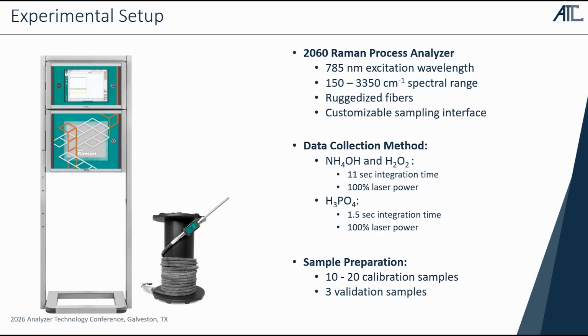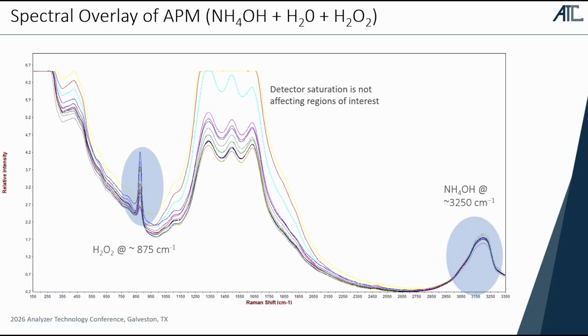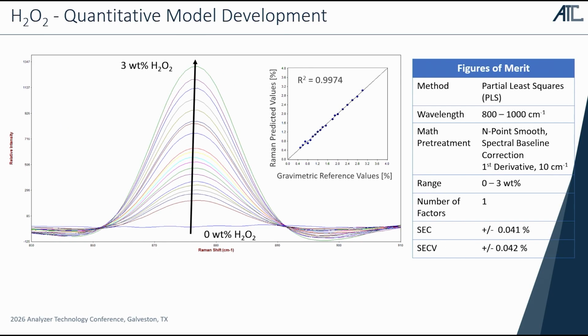And then we prepared the samples, had validation samples, ran through the whole application development. And I want to talk about how the spectra looked, how we did the model development, and what our conclusion is. So here we are looking at the spectral overlay of this APM etching bath solution. And you might say, well, there's again this detector saturation, part of the spectrum cannot be used. But if we look into where those components actually show up, it's at 875 and 3250. Those are the regions where we have very significant peaks representing the components in this etching bath. I zoomed in on one of those peaks so that you can see nicely with an increasing concentration, we also have an increase in this specific band representing hydrogen peroxide.